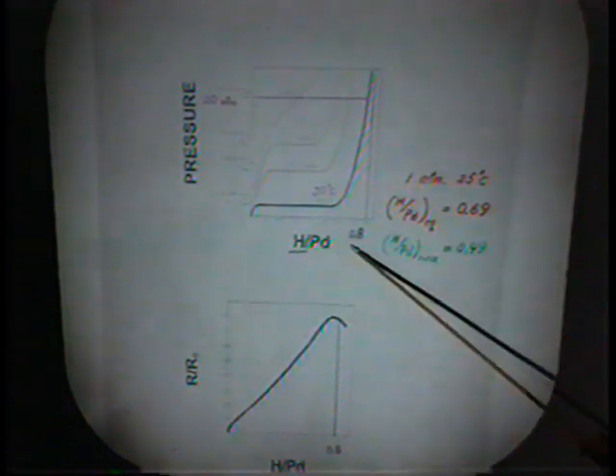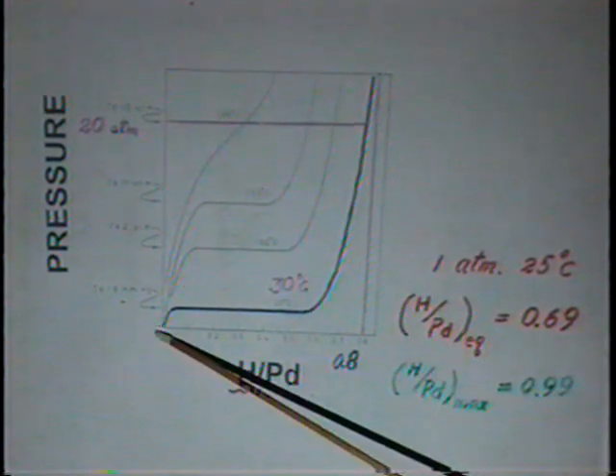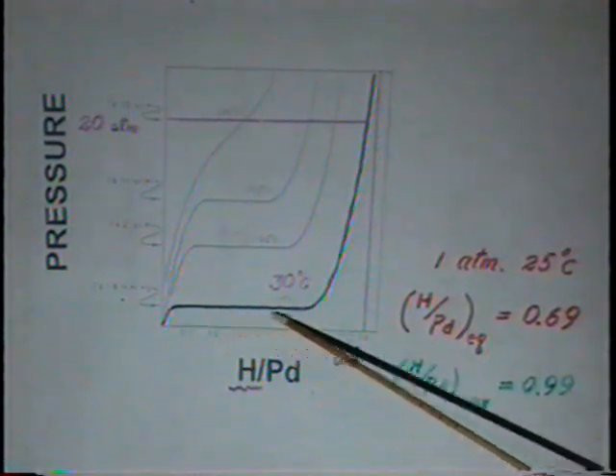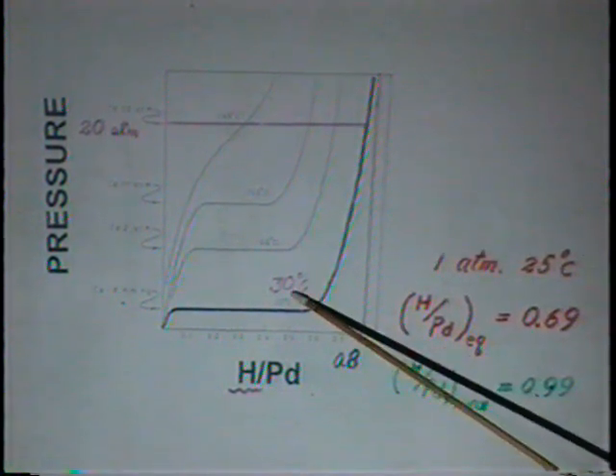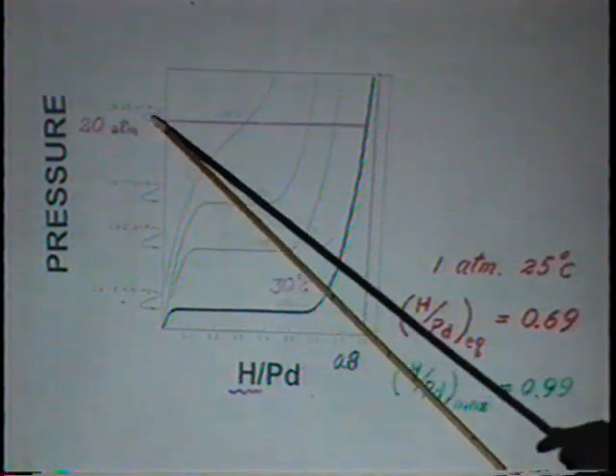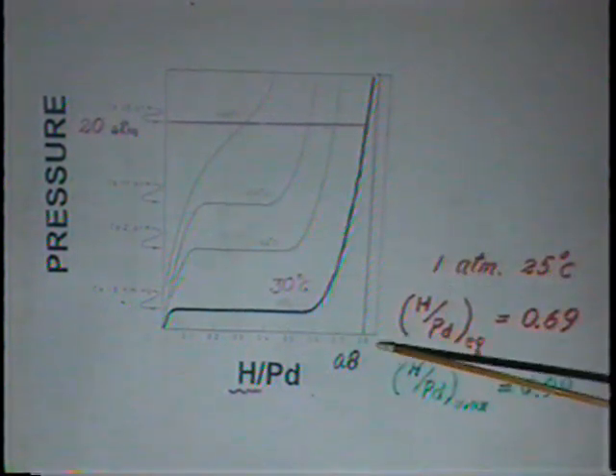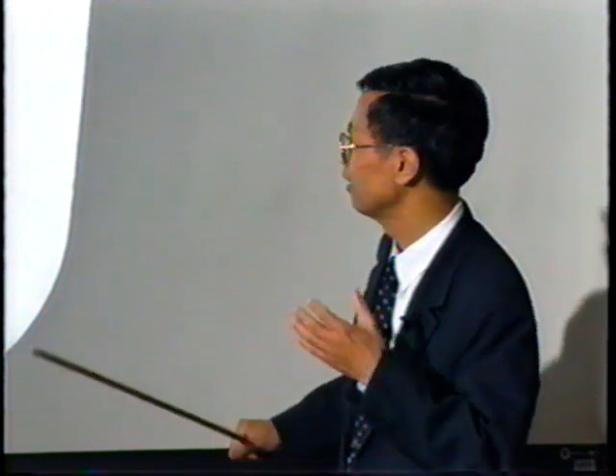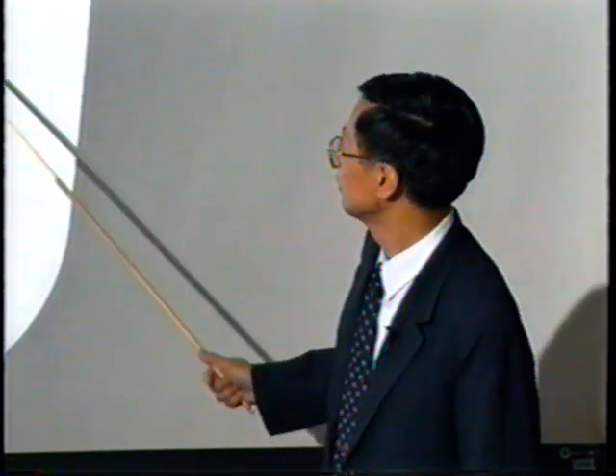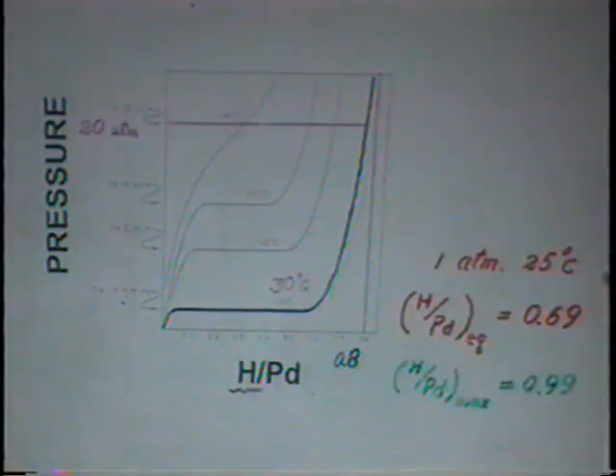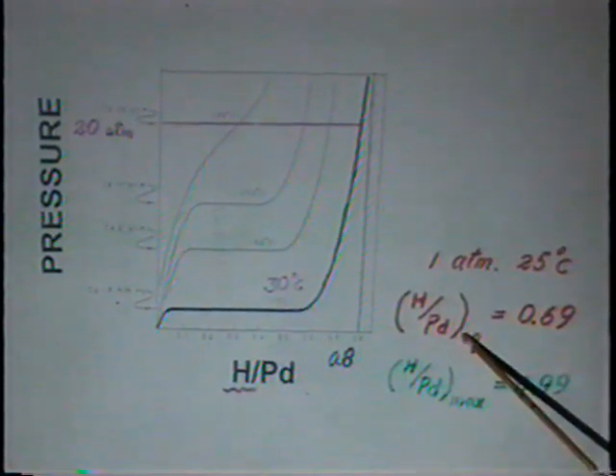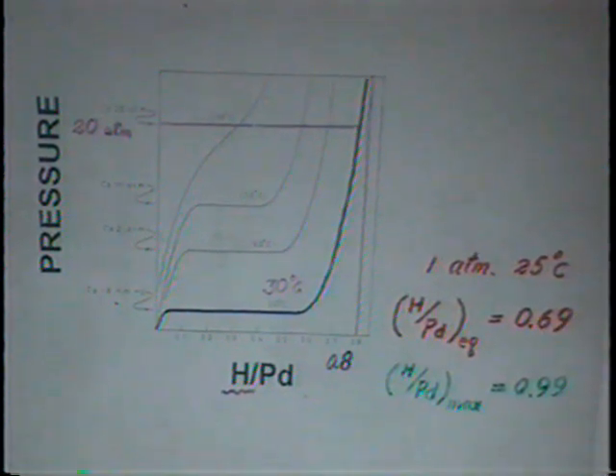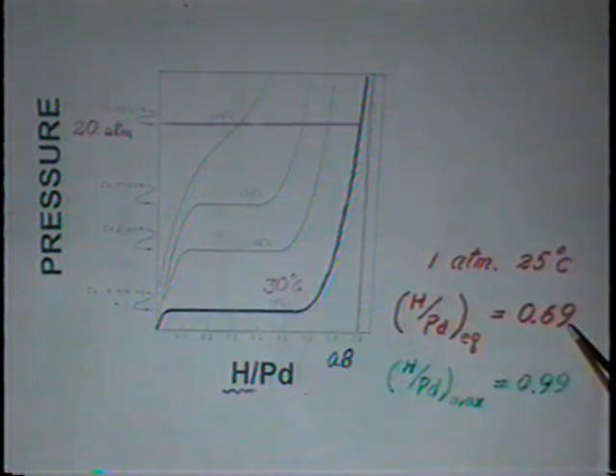But if we look at the phase diagram, that's for hydrogen. This is the pressure. This is the loading ratio. This is the curve at constant temperature. At 30 degrees C, if we reach 10 atmospheres, this number is much less than 0.8. So we didn't believe we could do this at a low temperature, room temperature, with the pressure we can reach. You see, this is the number from this kind of phase diagram. At 1 atmosphere, 25 degrees, the equilibrium number is 0.69. That's not good for cold fusion research. We need this number much greater than 0.8.